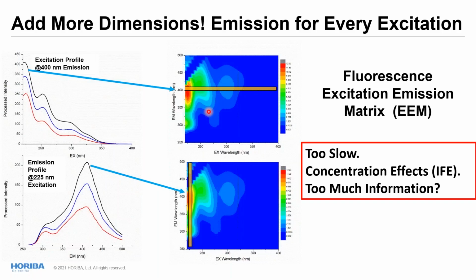But it is possible to correct for the IFE using an absorbance spectrum of the sample. That said, having to capture two different types of data, the EEM and separately an absorbance spectrum, is not only time consuming, but also the fact that you're using two different instruments to collect the data introduces error that results in an imperfect correction.